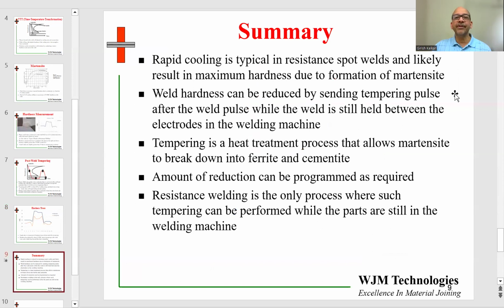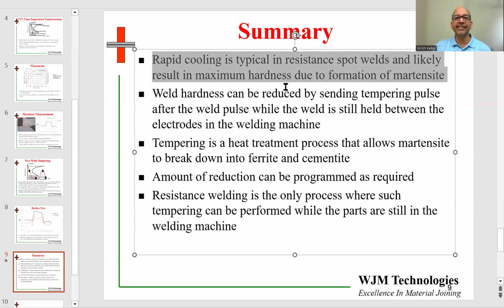So in summary, rapid cooling is very typical in resistance spot welds and likely to result in the maximum hardness due to formation of martensite. Resistance welding has electrodes in contact with the part, and often these electrodes are cooled with chilled water. At the end of the weld, the cooling rate in resistance welding is one of the highest in the welding processes, matched only, in some cases, by laser spot welding. So resistance spot welding and laser spot welding have the highest cooling rates. So it is very difficult to avoid formation of martensite in resistance spot welds.